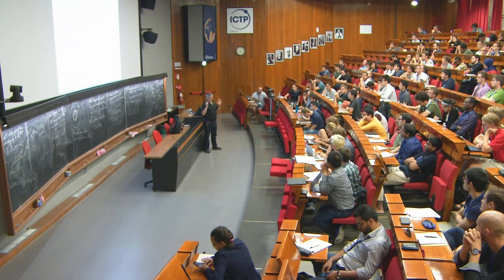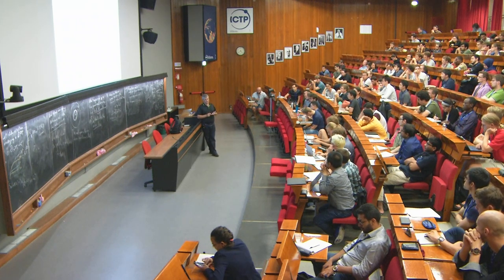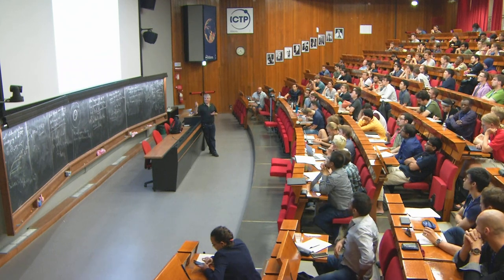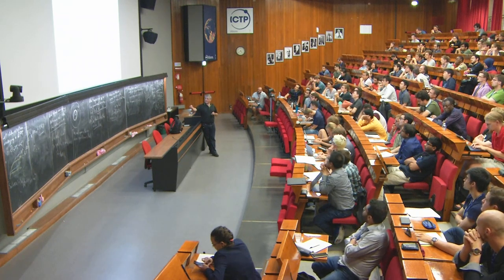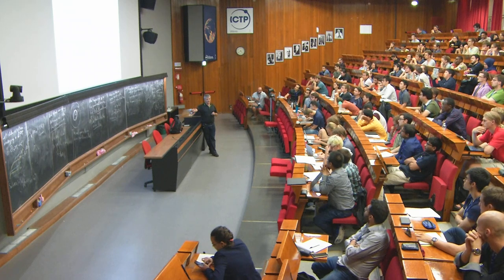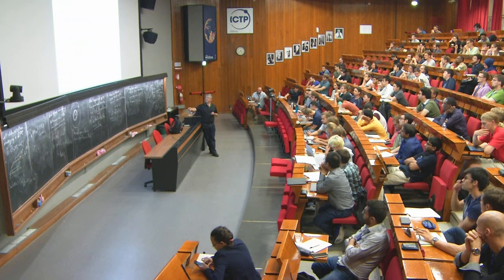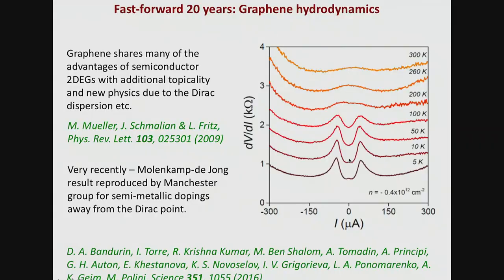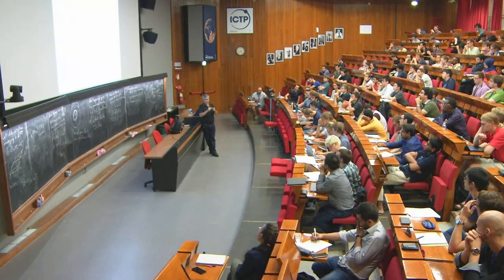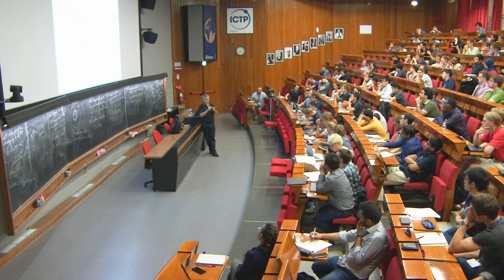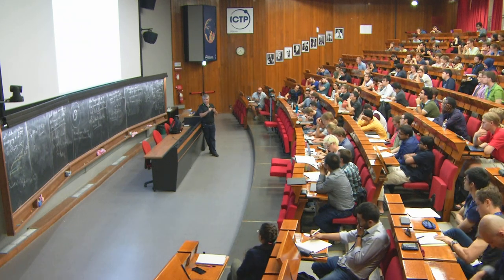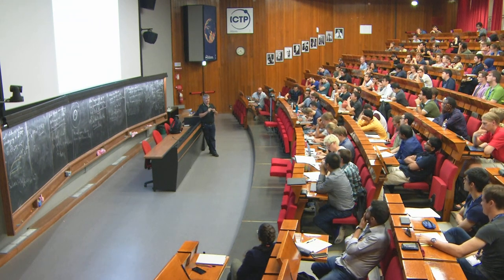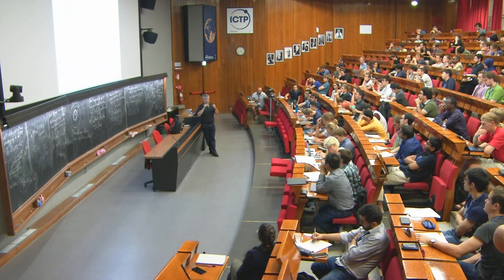Yeah, so graphene, there's two kinds of hydrodynamic regime because you have tuning. We're just about to see that when you dope graphene to semi-metallic dopings similar to the densities used in the semiconductor experiments, you can see very similar things in the differential resistance of graphene. You can also, though, try to tune graphene right towards the charge neutrality point. You run into some disorder effects, but there is a second regime of graphene where people have looked at thermal transport, where they claim that they can see huge differences from Fermi liquid thermal transport that they associate with being right in at the charge neutrality point. I'm going to mention those experiments, but I'm not going to describe them to you in much detail. What we're basically always considering today, because it allows us to compare different systems, are systems with at least semi-metallic densities.